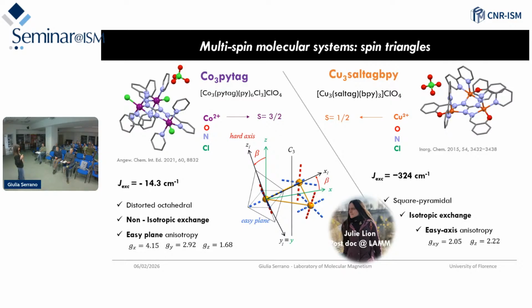For example, people doing ESR-STM, EPR-STM, are probing single ions or spin molecules on top of an MgO layer, because this is a much stiffer substrate. Basically, they don't see any spin signal on gold or normal metal. So a challenge, from a chemical point of view, is to deposit molecules, and a challenge for me is to create a spin qubit which has a ligand that really protects your spin well from the environment, from the surface.